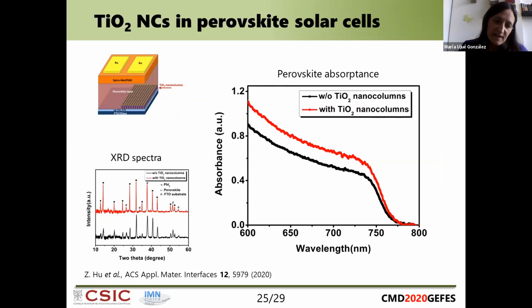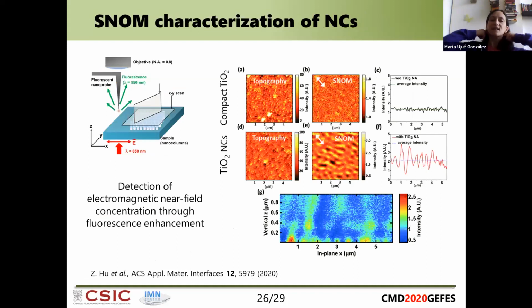So we see this as a first good point, maybe because the quality is a little bit better, but also maybe because we have this scattering effect: we have nanostructures that are modifying the optical properties, getting more scattering, and then increasing the absorbance of the perovskite. To check this, on top of some nanocolumns, before putting the perovskite, we performed some SNOM characterization again. This time we illuminated the area without and with nanocolumns, and we scanned with a tip with a fluorescent nanoparticle at the end, and the fluorescence of this nanoparticle will be higher when we have a bigger electromagnetic field.